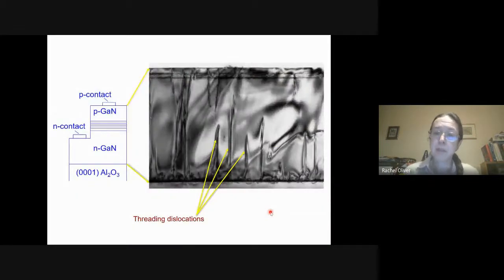Now, this is a simpler LED. This is one of the early LEDs grown at Cambridge. Still has the same key features, P-type and N-type gallium nitride, and quantum wells in between. It's a very, very simple LED. And we're now imaging it from the side. The previous image would have been looking down from the top. And we can see these lines running through it. And these are the actual lines of the dislocations.